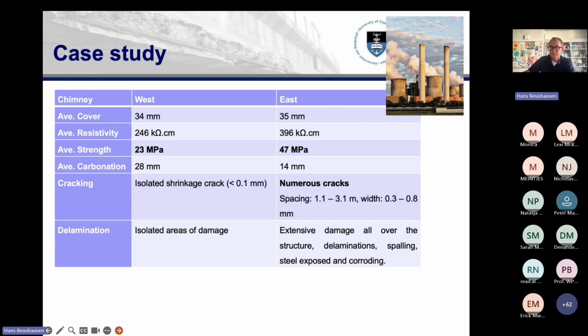So quite severe shrinkage cracking. Whereas the West Tower, the low strength concrete, had hardly any cracks at all. And the result was that the low strength tower had hardly any damage, whereas the East Tower, the high strength, the perceived high quality tower, even though it had better concrete properties as such in terms of carbonation resistance and resistivity, showed much more damage. And here are some pictures of that.